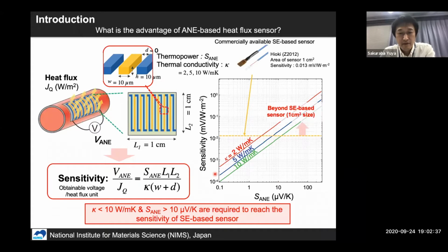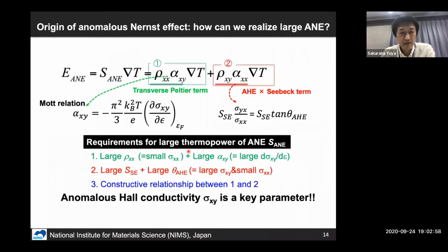So yeah, for both the energy harvesting and heat flux sensor, we have to realize a thermopower of over a few tens of microvolt per Kelvin. That is a clear requirement for realizing these kinds of thermoelectric applications. So here we need to consider how we can get a large thermoelectric power from the anomalous Nernst effect.